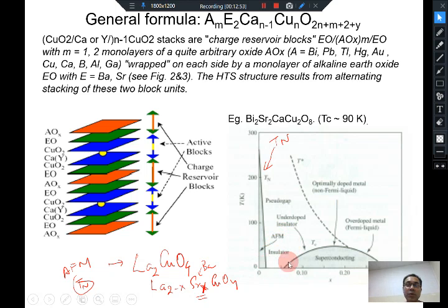Okay, now once it loses this antiferromagnetic order, below this line it is an antiferromagnetic insulator as shown here. Now between this, in a certain doping range, the system behaves like a very strange metal. Here the material is completely not like that of an ordinary metal, but the resistivity depends linearly on temperature, and various other unusual features happen in this regime, where the material is neither an antiferromagnetic insulator nor superconducting, but it is a strange metal. Okay, this area has recently become very interesting and important for investigations because of these unusual properties.